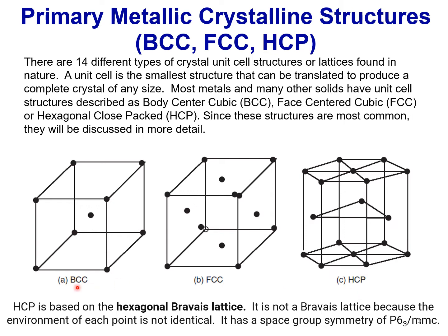The BCC is less important than the other two, but BCC is the beta phase. It's the structure of the beta phase in zirconium pressure tubes. In zirconium pressure tubes, you have a hexagonal close packed alpha phase interspersed with filaments or layers of body-centered cubic beta phase. So that's why these two crystal structures are here amongst the ones that you will likely come across the most.